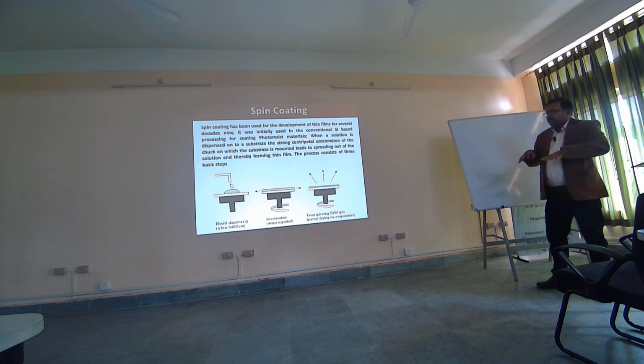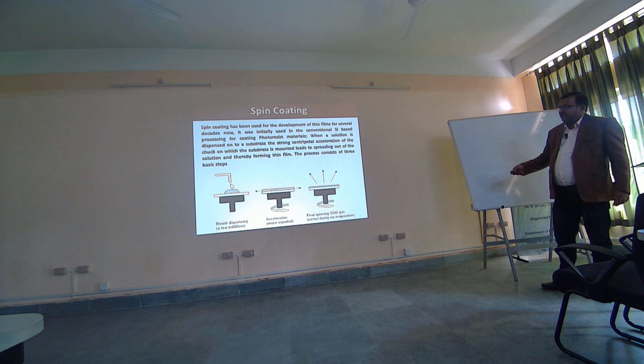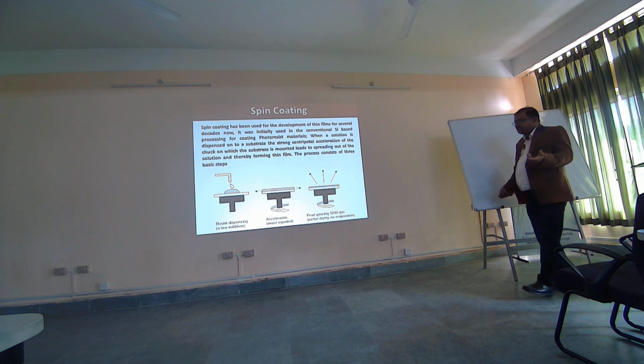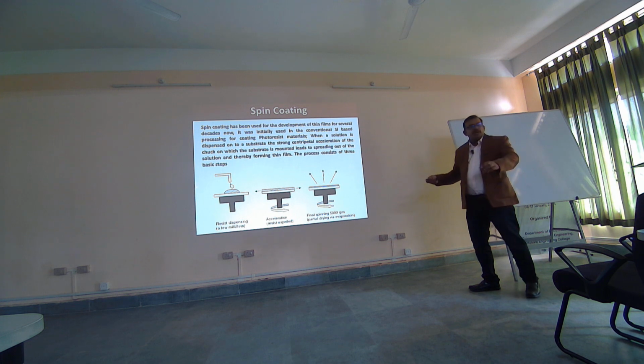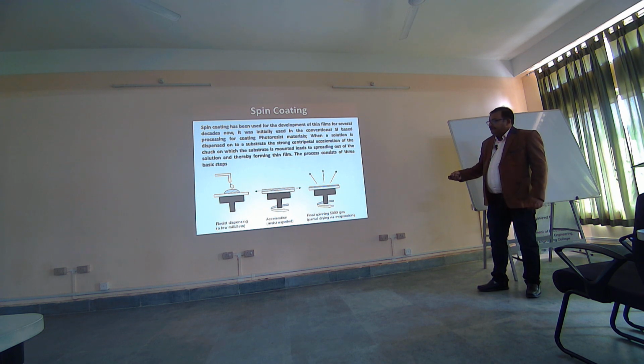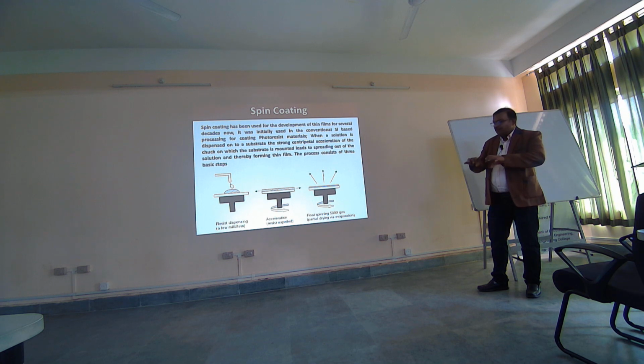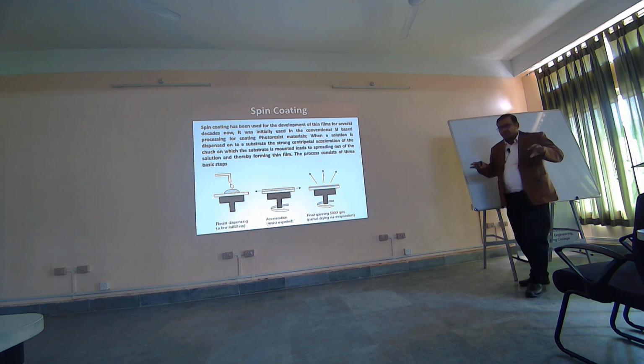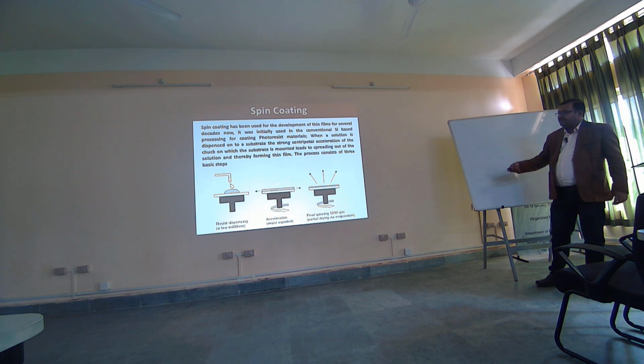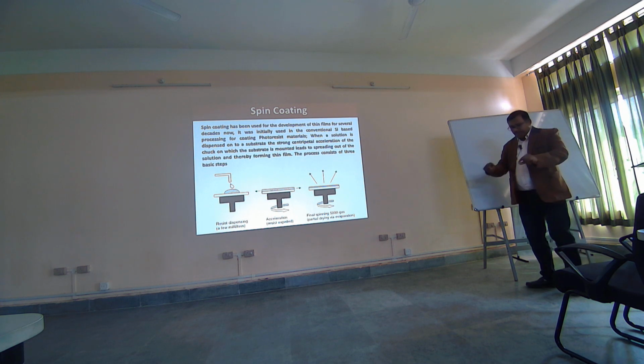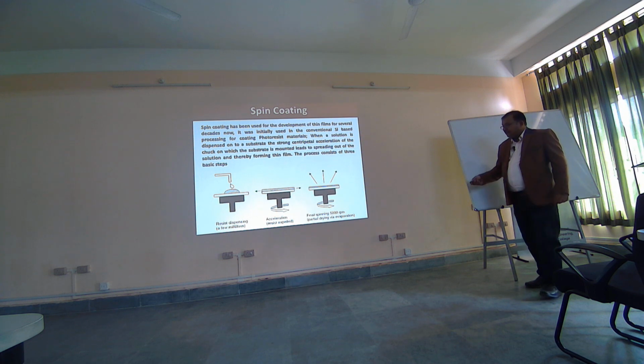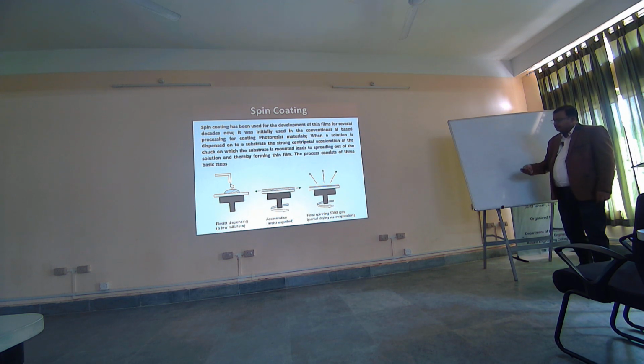fills out the entire substrate surface, and because of the rapid rotation, and usually the solvent used is volatile, for example chloroform. Chloroform is a very volatile solvent. So what happens is it evaporates, and the solid that is left is your thin film of the molecule, or molecular thin film of the material that you wanted to coat. So you end up getting this kind of thin film by rotating the substrate at typical speeds of 1000 or 2000 rpm.